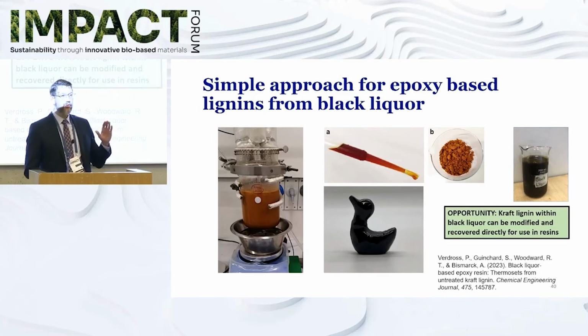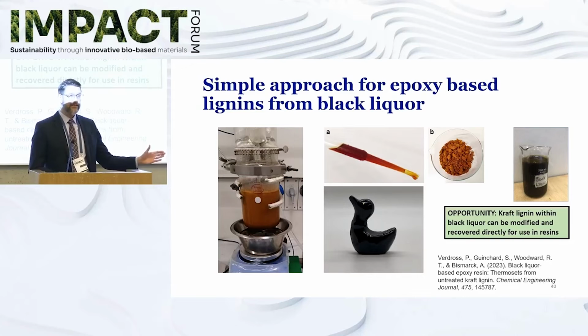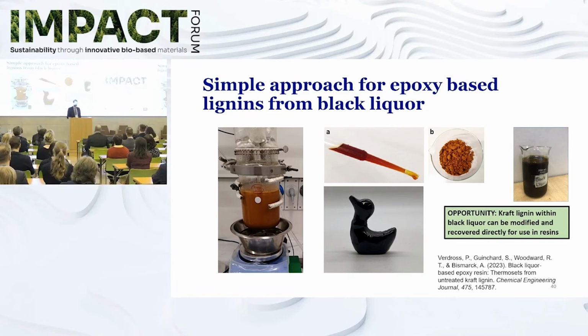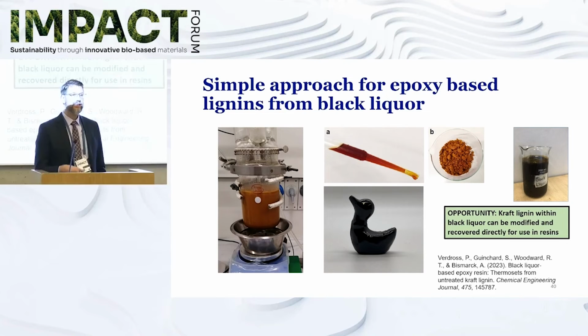If you want to think more about kraft lignin, you can take black liquor. There's some nice work from the University of Vienna where they made an emulsion of the black liquor, reacted the lignin directly in it, epoxidized it, and then recovered this nice epoxidized lignin powder. That could be mixed with different types of hardeners to make this epoxy resin cured material. So that works out pretty great there.